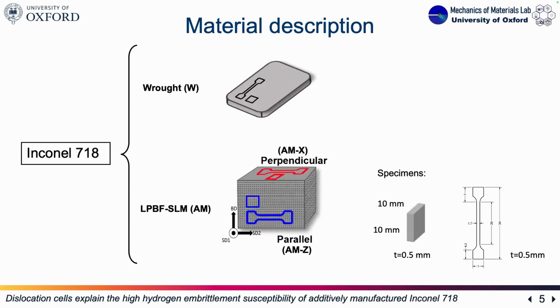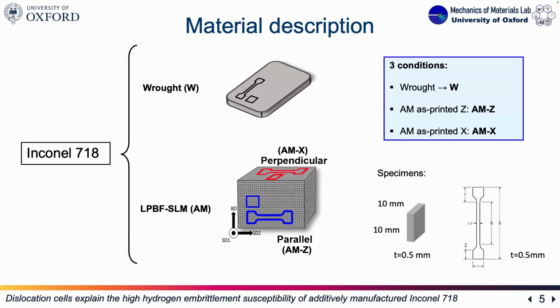Let's say that we have studied two conditions of Inconel: wrought, from a hot rolled and annealed slab, and then the laser powder bed fusion, selective laser melted, additively manufactured Inconel in two directions. And to do so, we have employed small TDS samples, like these ones, 10 by 10 with a small thickness, and also pretty little tensile samples like dog bone specimens.